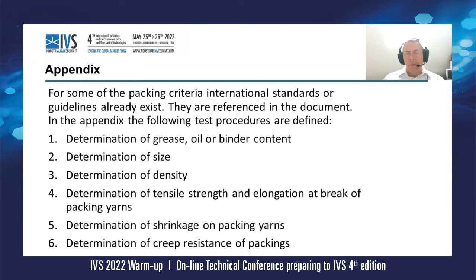Some of the packing criteria mentioned in the standard, international standards or guidelines are already in existence. They are all referenced in the document. But then again, we also produced a quite extensive appendix for test procedures that had to be defined to make sure that the quality standards can be met. So the first one is the determination of the grease, oil or binder content, the determination of the size, the determination of the density, and again, the tables shown in the previous slides, the determination of tensile strength and the elongation at break of packing yarns, the determination of shrinkage of the packing yarns, and the determination of the creep resistance of the packings. They all have been defined in an extensive appendix, and specific methods are given.